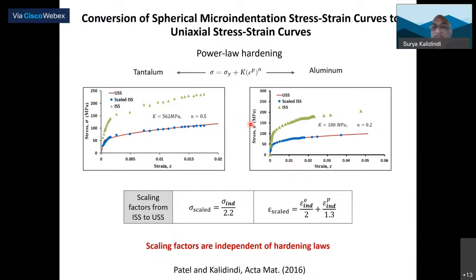So those are indentation quantities. How do you convert them to uniaxial quantities? We went through a lot of finite element simulations again, where we can prescribe the physics. So we said, if we assume that the material is isotropic and just does J2 flow theory, how do I convert? It turns out you only need 3 scaling factors. And if you apply these 3 scaling factors, you'll get a very good match between the uniaxial curve.